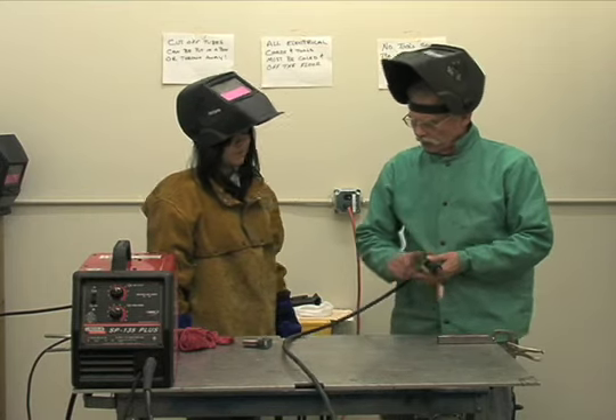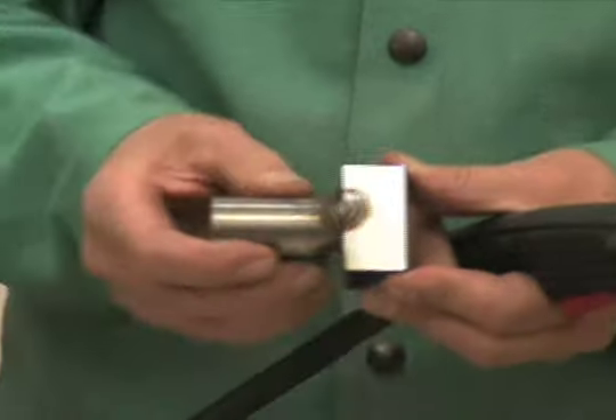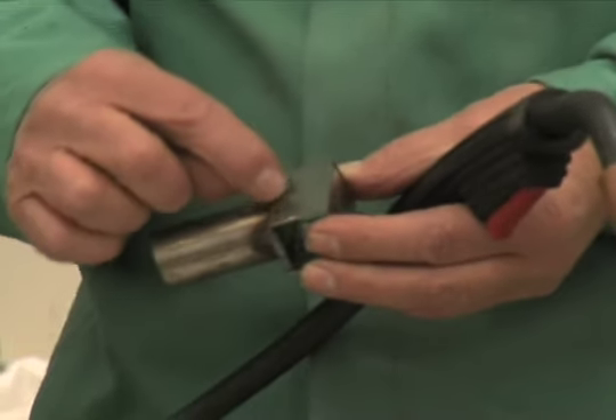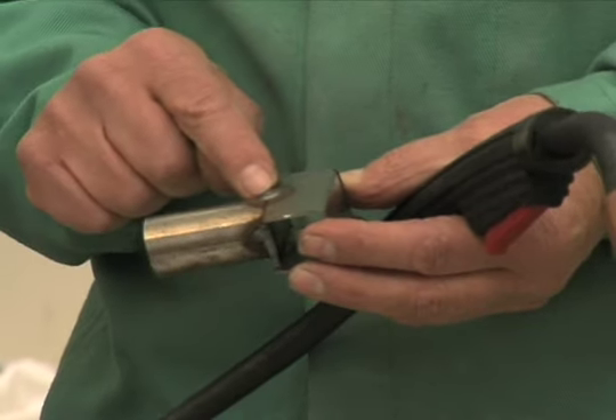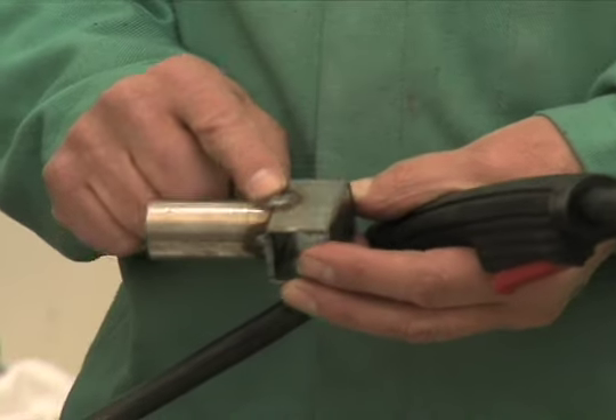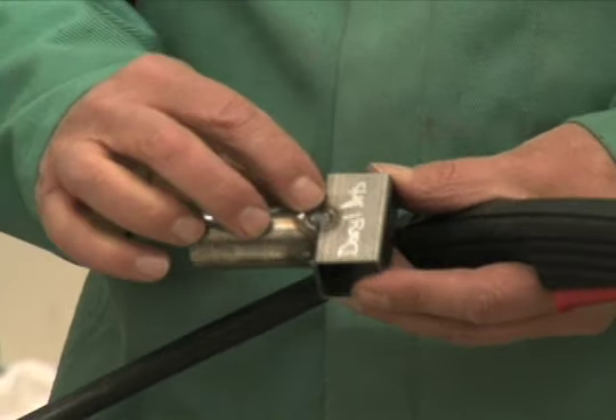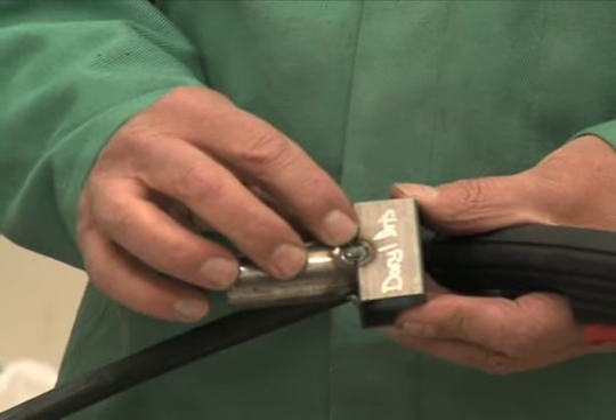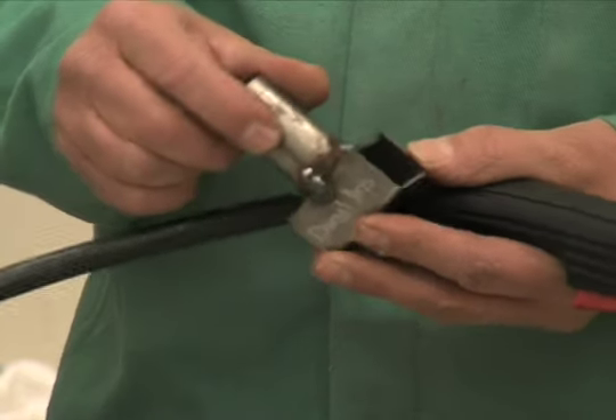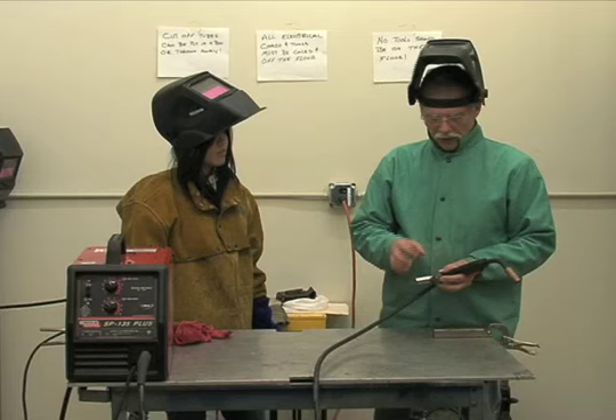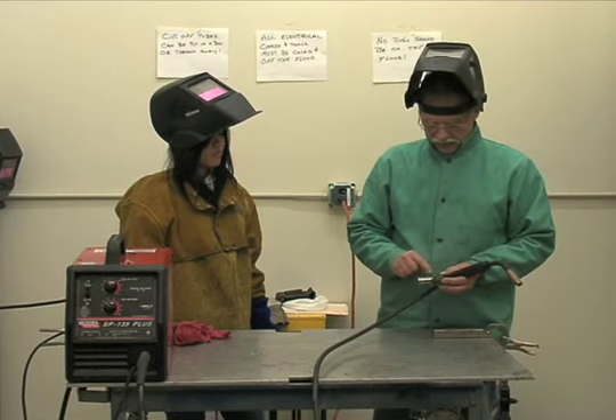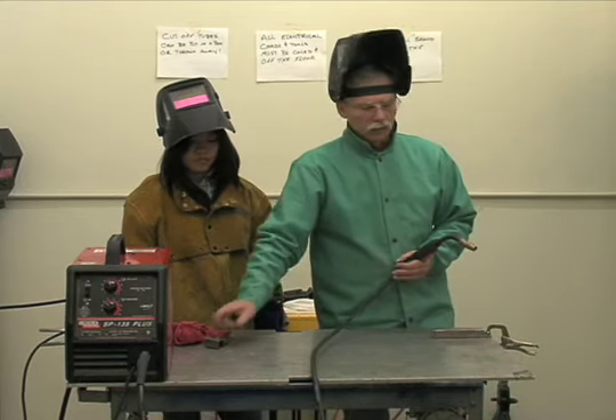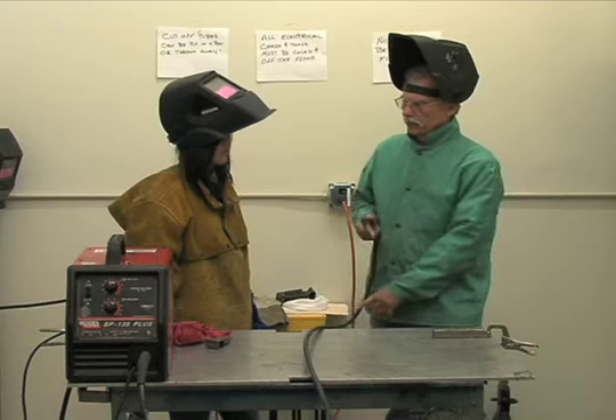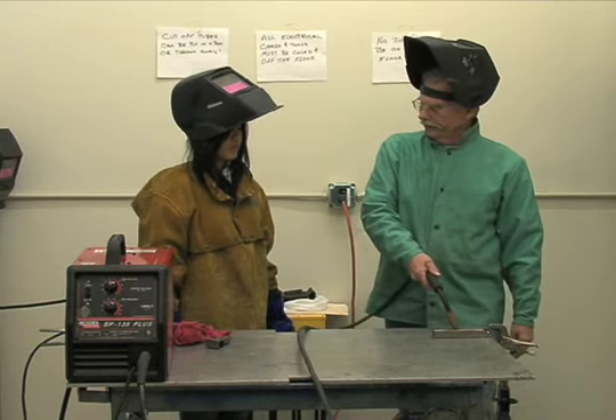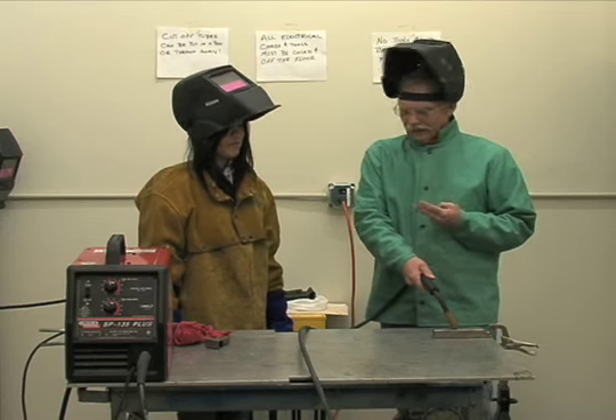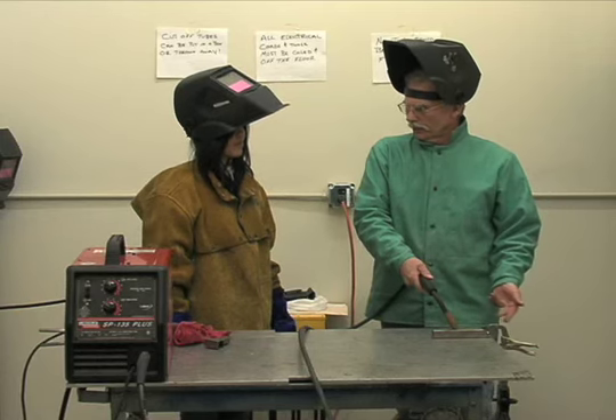It actually will create heat circles in the metal. So if you look right here, see the diameter of this color change in the metal? That heated more than adequately to bring it up. If you look at this one, smaller. This one took place in a shorter period of time. So what we want to do is to give it enough to where we both deposit enough filler material and heat the metal up to molten. The biggest problem with spot welds is they're cold. There's not enough time been given to them. What's the number? 2 full seconds, right? 1 California, 2 California, release.